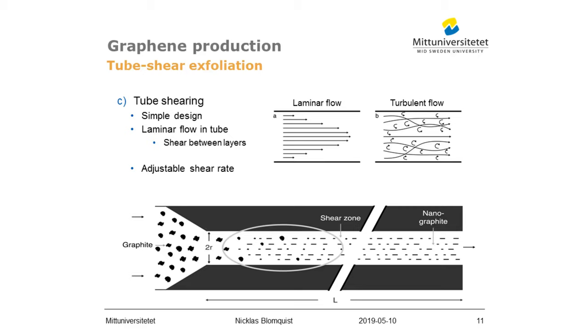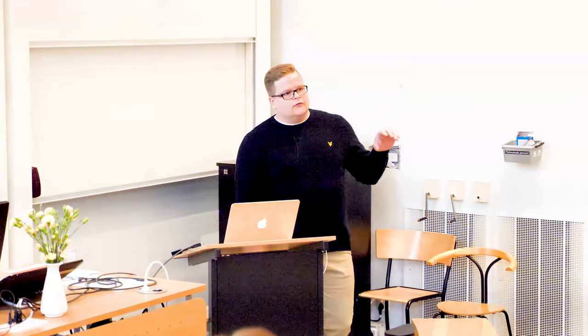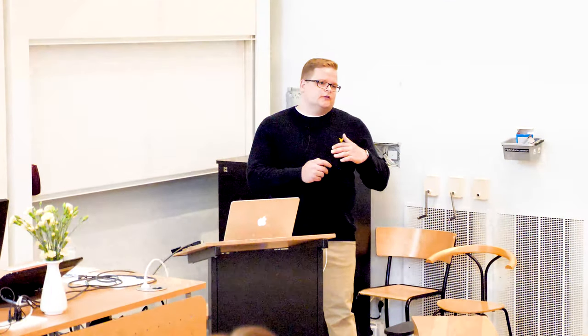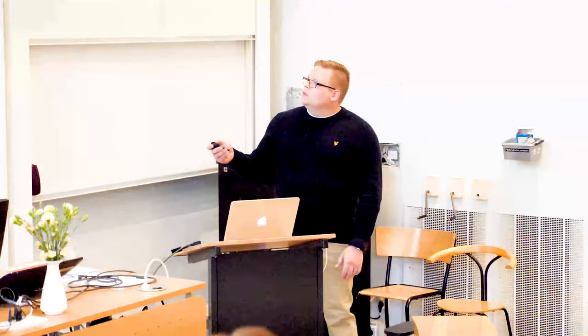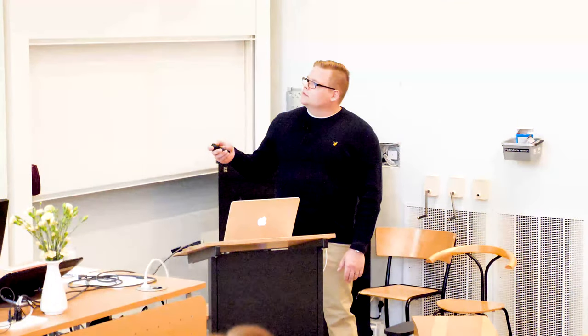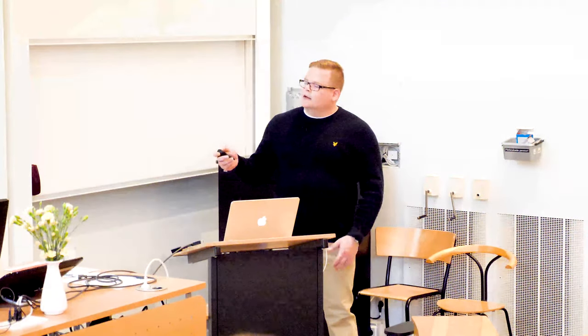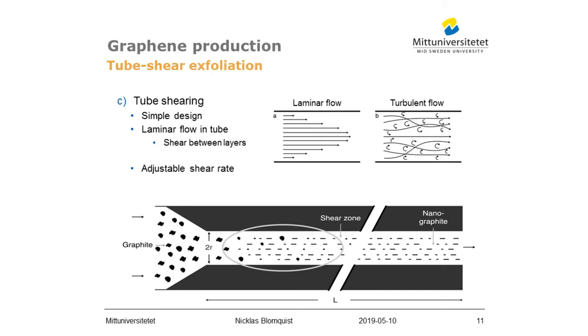When we have laminar flow in a tube, the fluid velocity in the center is higher than close to the tube wall. And this means that we have several fluid layers with different velocities inside the tube. And in between these layers, we get shear forces. When the flow gets more turbulent, we get a more chaotic situation. We have big lateral mixing, we have high and low speed regions, and a big possibility of collision and cracking the flakes.